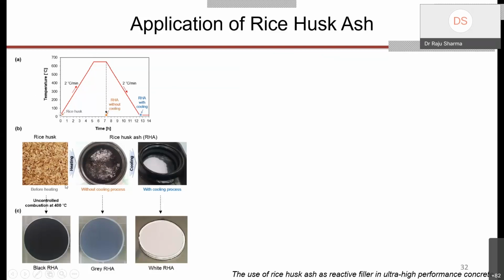So if you see the B image, you can see the rice husk before heating, and then when you burn it with uncontrolled combustion at 400 degrees Celsius, as you can get from any industry, that is unburned, uncontrolled combustion, so you get a black RHA, right? It means that there is a lot of unburned carbon, and when you process it to 7 hours and just take it out without cooling, you get a gray kind of RHA. When you allow it to cool, you get a white kind of RHA. So these are the different forms you can get.